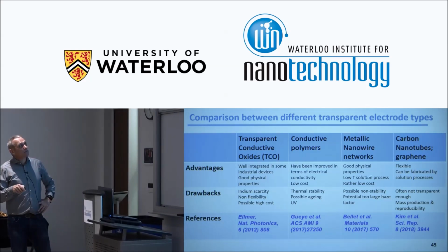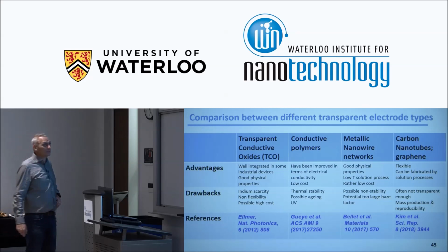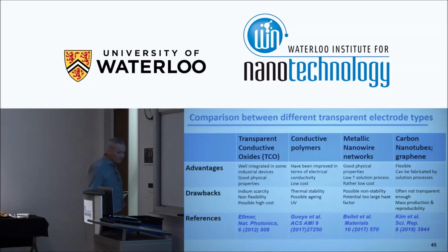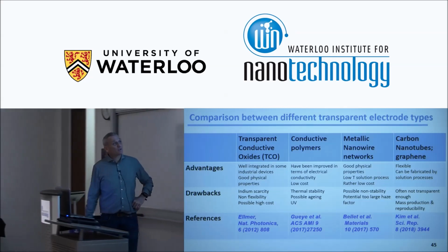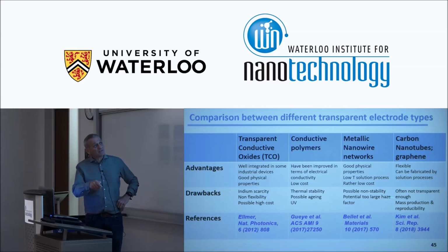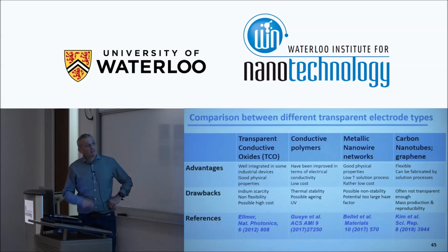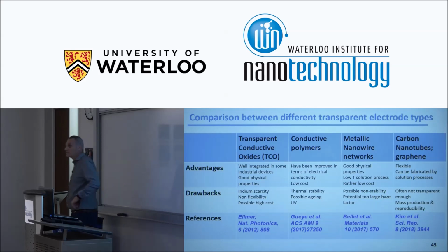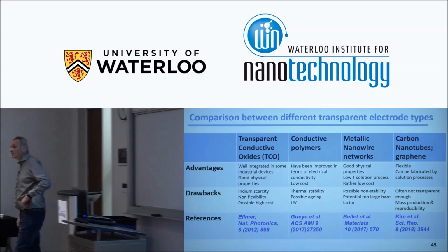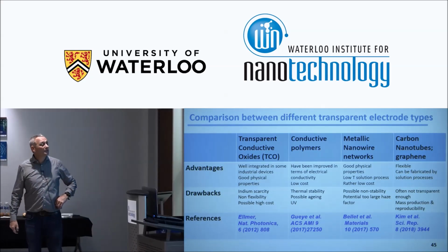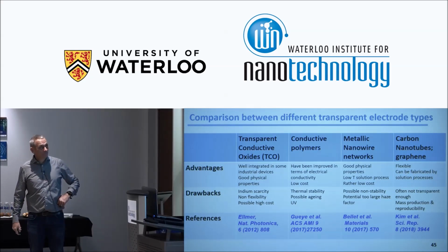Metallic nanowire networks have rather good or even very good physical properties. They are compatible with low temperature solution process fabrication, so low cost as well, and compatible with roll-to-roll and so on. There might be some problems with stability, so we have to be careful with that. For some applications, there would be too large a haze factor. That might be a problem for display applications, for example, for smart grids or smart windows integration.